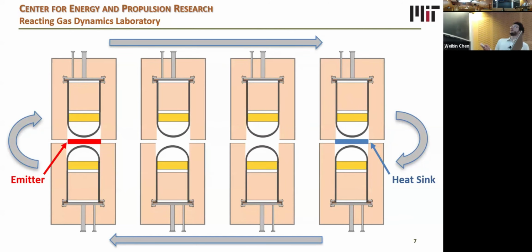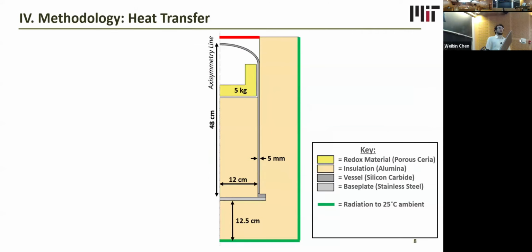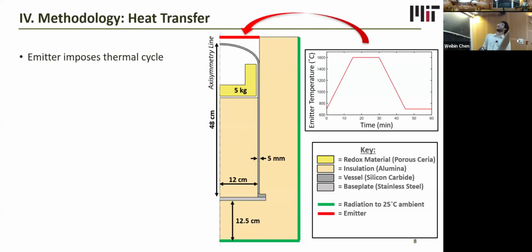So this is what the reactor would look like in an 8-reactor RTS, cycling between the hot emitter and the heat sink side, and it's always facing each other. So to model the heat transfer and mechanics of the system, we created a finite element model of it in COMSOL Multiphysics. And the dimensions you see here are not finalized or optimized, but this is an example that we will be using to show some sample results.